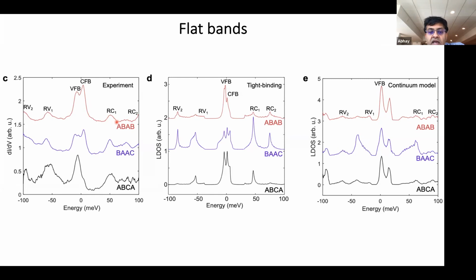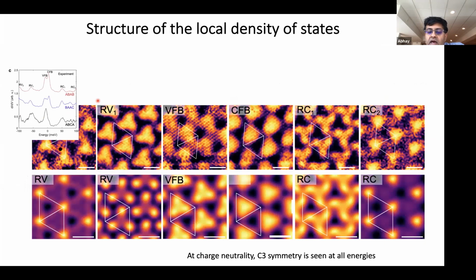And we were able to use theory to confirm exactly what we see in experiment, to show that our spectroscopy matches what one expects for single particle theory, both by DFT and analytical methods. One really nice aspect of this system is that the local density of states, the wave functions of this material, are incredibly rich and complex. Here I'm showing you wave functions or local density of states at different energies.